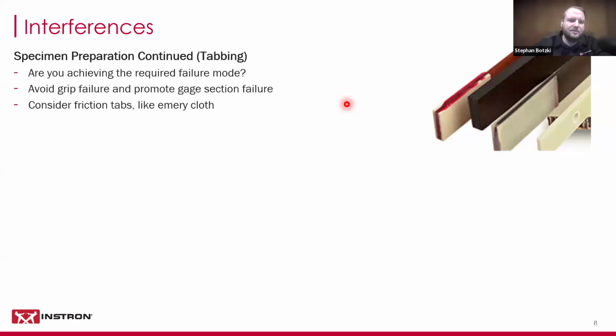And what you could start with is something like friction tabs, like emery cloth or sandpaper, with the rough side, which is usually what has been successful for me personally. If you use the rough side of the sandpaper, you put that around your test specimen ends, and then you clamp onto that with your grips. That has definitely helped me personally to achieve the right failure modes and also get them in the gauge section of the specimen. Now, sometimes friction tabs alone are not sufficient, and then you need to really have bonded tabs that are basically glued to your test specimen with an adhesive.